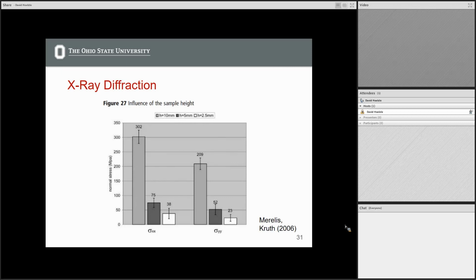And the main takeaway here is that as you build up the part, going from 2.5 millimeters to 10 millimeters of part height, you get a really, really big increase in your residual stress buildup. In fact, we're beginning to push the yield stress of the material itself. So we're going to get yielding just through the printing process from our intended net shape that we can't anneal out.